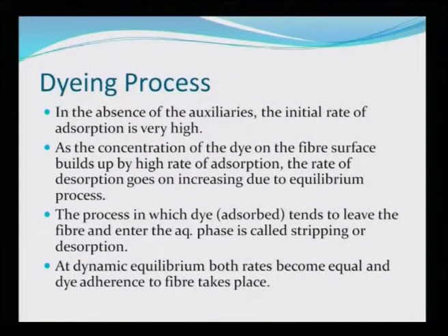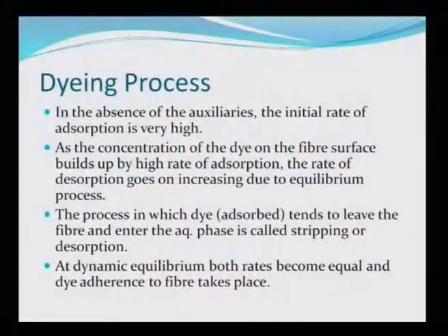So, in the absence of auxiliaries, the initial rate of adsorption is very high. As the concentration of the dye on the fiber surface builds up by the high rate of adsorption, the rate of desorption goes on increasing due to the equilibrium process. So, here again there is a forward reaction where the dye is actually being adsorbed, and there is a desorption reaction happening simultaneously after some time when the concentration of the dye in the fabric has increased enough.